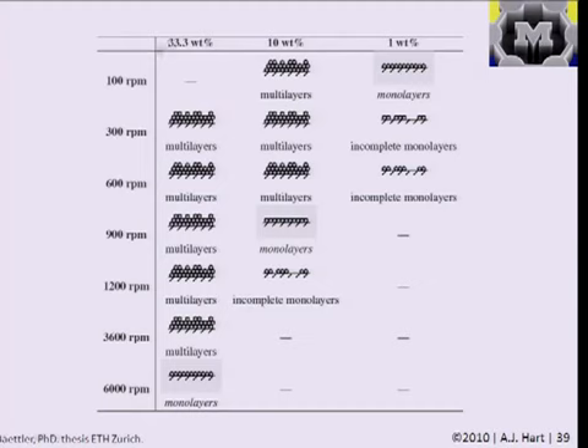So we see here at this high concentration of particles, increasing the spin speed went from multi-layer structures to eventually having single-layer structures. And here he's not really talking about the specific packing, but just the number of layers that resulted. So faster spin speed took the particles away more quickly. If you go down in concentration at the same spin speed, you saw, for example, that the number of layers also decreased. And in the case of having a much smaller concentration, only 1% of the particles at this spin speed of 100 RPM, he achieved monolayers, but at higher speeds, he achieved incomplete